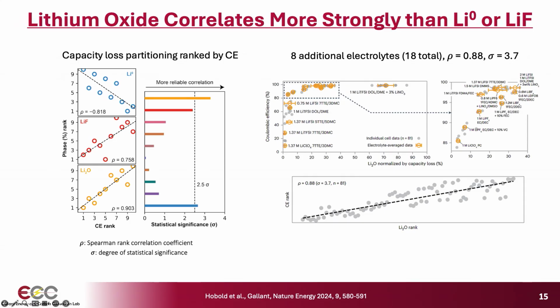We expanded the data set further. We looked at 8 additional electrolytes for a total of 18. You see here the relationship between Coulombic efficiency and lithium oxide content in the SEI, and the statistical significance actually increased further.